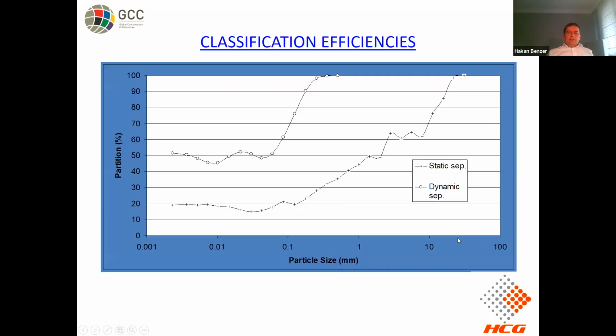So as you see, there are two classifications happening, and as expected, very inefficient static separation because of the pneumatic transportation system. Generally speaking, a high efficient classifier is being used in the vertical roller mills to achieve the final product. But the major problem is inevitably we have no chance to carry the whole material up to the classifier, and this makes a very high circulating load within the system. You may think that this is very inefficient, but in terms of the design conditions, this has been taken into account, and therefore the producers select a bigger motor size in order to achieve a certain grind size.